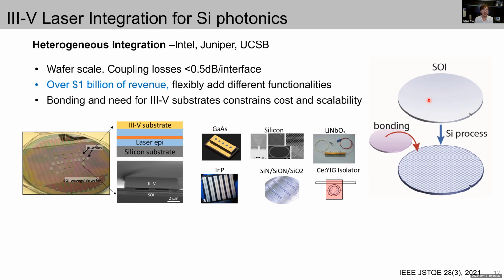So actually, thermal is a big problem for the SOI substrate, because there is a 1 micron oxide. This is very bad for thermal dissipation. So what we do is add a thermal shunt so that we can conduct the heat from a laser directly to the silicon substrate. This is one strategy to overcome the heat problems, but we definitely need more optimization.